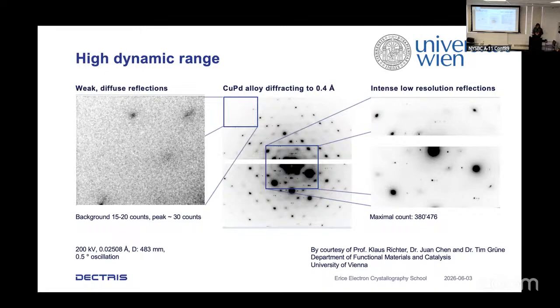What I mean by high dynamic range, this is data from Tim's group collected in Vienna with a single detector, where they have data of a copper palladium alloy with 380,000 counts in the highest peak in this 0.5 degree oscillation at 200 kilovolt, and the diffuse background at about 0.4 angstrom resolution is about 15 to 20 counts, and you can see nicely peaks of about 30 counts in this far corner. So you have the almost 400,000 count peak and the 30 count peak in the same image, and this works perfectly well.